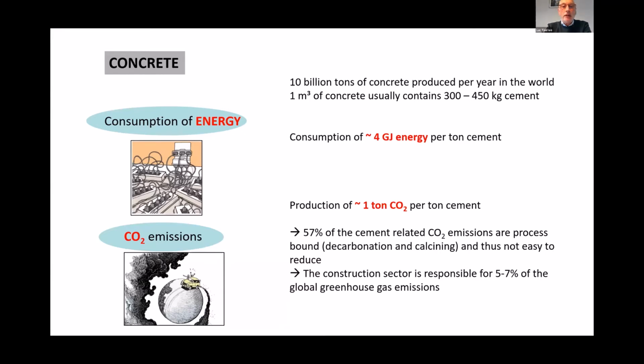A huge amount of concrete is produced every year in the world, 10 billion tons of concrete, and 1 cubic meter of concrete usually contains about 345 kilograms of cement. This corresponds to an energy consumption of about 4 gigajoule per ton cement, and what is worse, 1 ton CO2 is produced per ton cement. So this means that 57% of cement-related CO2 emissions are process-bound. I will show you the decarbonation and calcining. And the construction sector is responsible for 5 to 7% of the global greenhouse gas emissions. So this is a huge